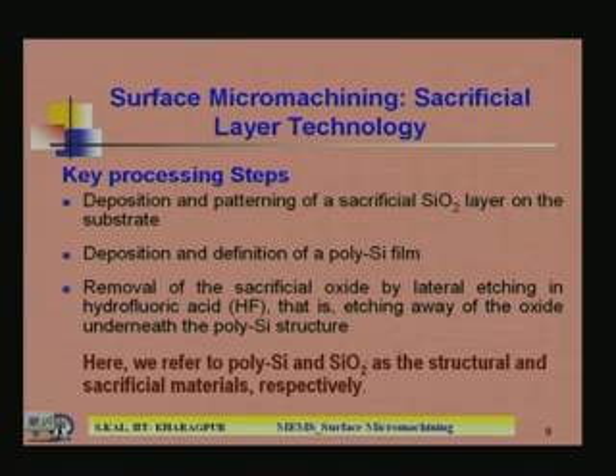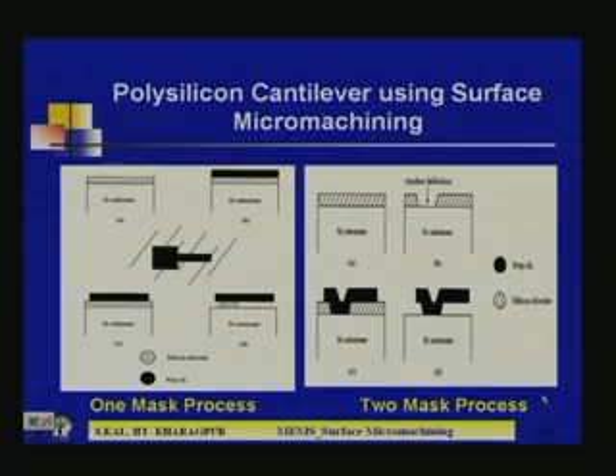You do not need selectivity with silicon, but in some applications if you want to make this structure on silicon, then you have to go for buffered hydrofluoric acid, because BHF does not attack silicon, it will attack only silicon dioxide. Okay. Now, etching away the oxide underneath the polysilicon structure, here we refer to polysilicon and silicon dioxide as the structural and sacrificial materials respectively.